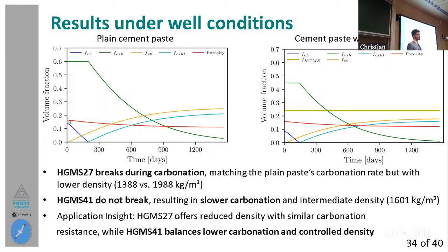So first, in blue, you will see the consumption of the calcium hydroxide during carbonation, which is the first thing that is happening here, which results in a precipitation of calcium carbonate, which is the orange phase there. Then, once the calcium hydroxide is completely consumed, we begin the consumption of the calcium silicate hydrate, and this results also in an increase in the calcium carbonate phase, and the leached silica in light blue there. We also have, which is interesting to note, a slight decrease in the porosity, which is this red line there, due to the higher molar volume of the calcium carbonate with respect to the cement hydration products.